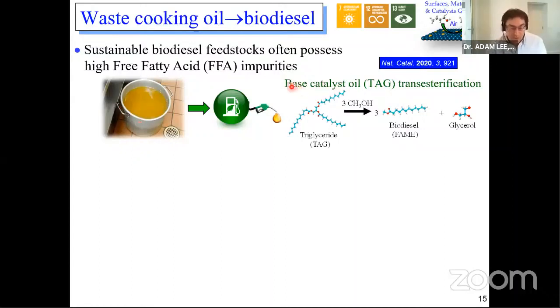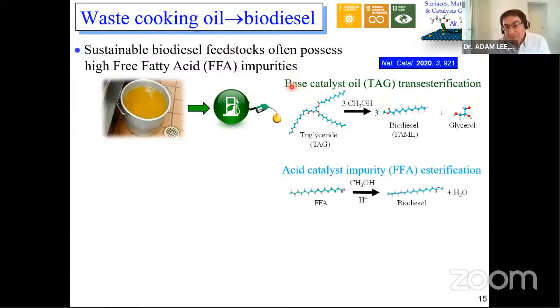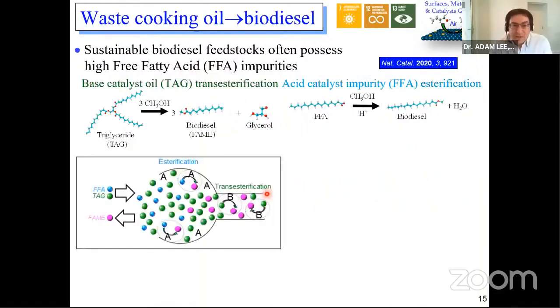So we were trying to work out, could we create a new spatially orthogonal catalyst that could overcome this by including an acid catalyst inside the particle? Acid catalysts are actually really good at removing these free fatty acid impurities. So our idea is that we could make a catalyst that would have essentially two types of active sites inside it. In these big pores, we would have acid catalysts that would allow us to do the free fatty acid impurity removal. So in this pore here, we would do an esterification.